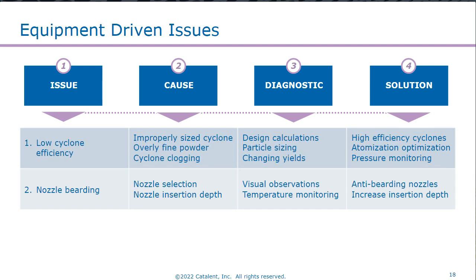Some equipment-driven troubleshooting issues include low cyclone efficiency. This can be caused by an improperly sized cyclone. Perhaps we're pushing process throughput and we're now operating in a regime that the cyclone wasn't originally designed for. Perhaps we're creating a lot of fine powder. Or one that often creeps up is if you have material sticking on the wall of your chamber, and then if your pneumatic hammers knock that material off, you can clog or overload your cyclone.